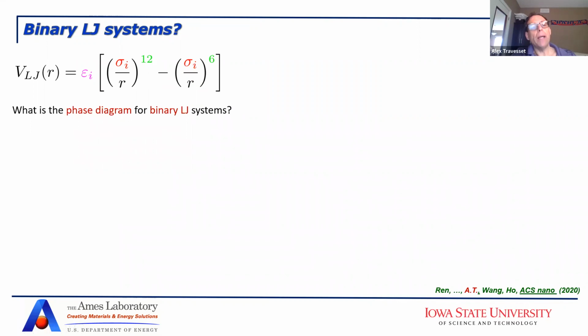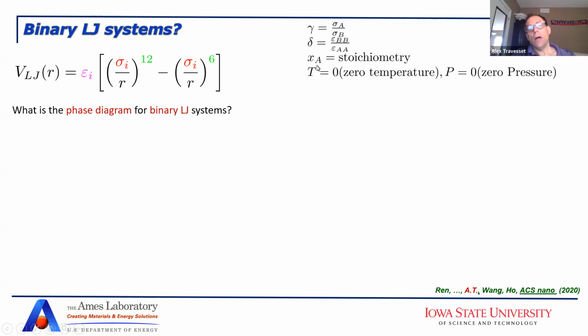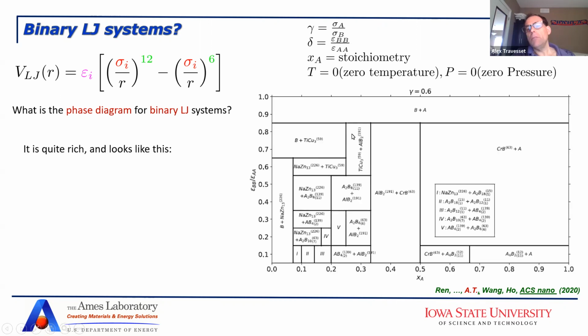We actually went and computed the phase diagram of binary Lennard-Jones systems, where you have two types of diameters and also two types of interactions. The A-B interaction would be just the arithmetic mean. The phase diagram depends on many parameters, but let me tell you what happens when you put 0.6 here, and then you have this other parameter at 0 temperature and 0 pressure. That's not a big restriction.